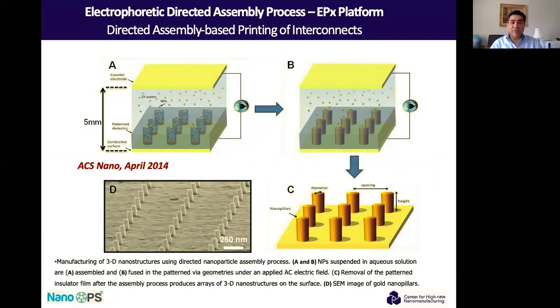So this one is electrophoretic directed assembly, which means that you apply a voltage electric field to attract the particles. This particular slide shows interconnects. We have vias, which are cylindrical holes that could be in photoresist, or an oxide, or any material that your device requires. Then you turn on about 1 or 2 volts, and the particles will assemble and fully fill all the vias, and then they fuse on their own. In less than a minute the process is done, and you can do a whole wafer in about 30 seconds to a minute, for example.